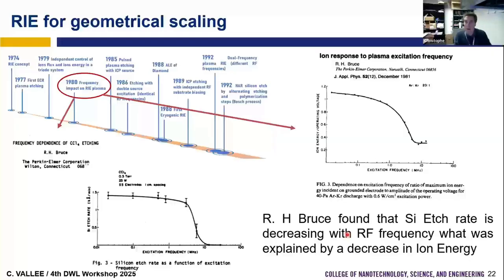And yes, we can have a decoupling with a CCP reactor by playing with frequency. So I go back to my timeline and I will take this paper where we have the frequency impact on RIE. This is the first paper from Robert Bruce, where he studied the frequency dependence for etching with CCl4. What he observed for silicon etching is that if we change the excitation frequency of a single frequency generator, going from low frequency to high frequency, you have a huge drop of the etching rate.